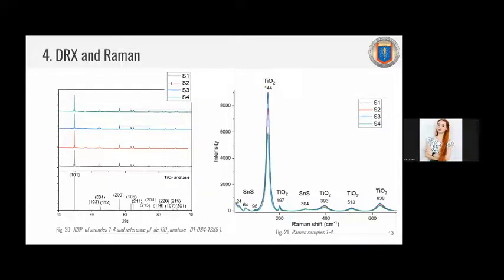Also, X-ray was done to the samples. In the X-ray results, which you can see in the figure on the left, we can see peaks referring to titanium dioxide only, no tin sulfide, because the amount of tin sulfide quantum dots was very low, and the sensitivity of X-ray does not identify this material. So we only have titanium dioxide in X-ray, but hence we did Raman spectroscopy because it has more sensitivity, and in Raman we could observe peaks of orthorhombic tin sulfide crystals. The peaks were 24, 64, 98, and 304, and the rest of the peaks belong to titanium dioxide.